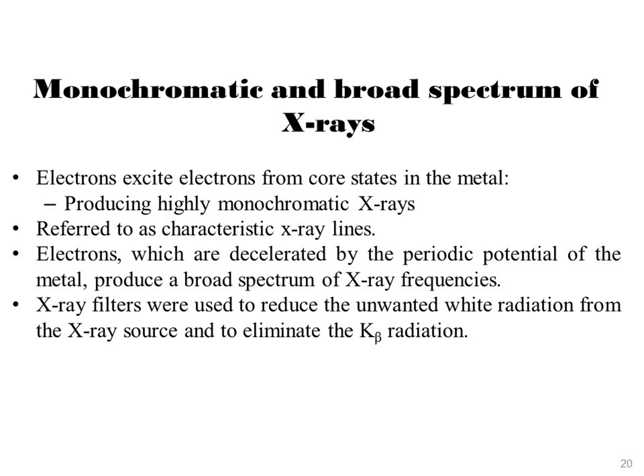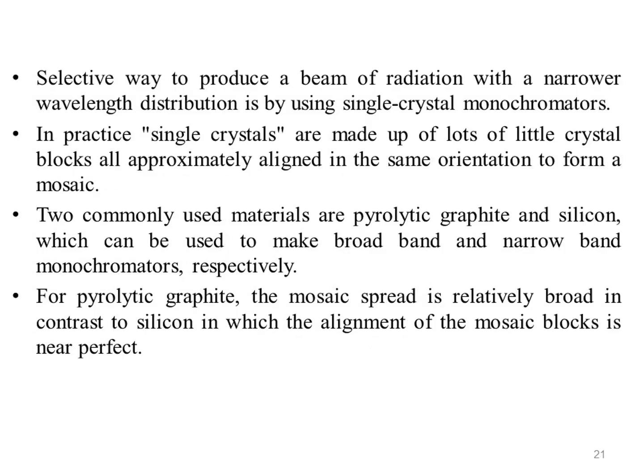Historically, X-ray filters were used to reduce the unwanted white radiation from the X-ray source and to eliminate the K beta radiation as much as possible. The drawback of filters is that the background radiation is still high and that the transmitted radiation is still not very monochromatic. An alternative and more selective way to produce a beam of radiation with a narrower wavelength distribution is by using single crystal monochromators.